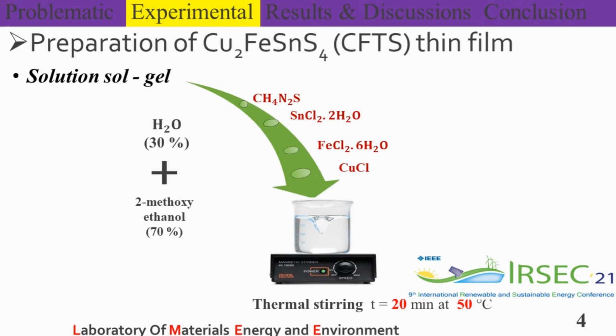Firstly, I will present the part of experimental section concerned to synthesis of CFTS thin film solar cells by sol-gel spin coating technique. The precursors used to prepare the sol-gel solution were copper chloride, iron chloride, tin chloride, and urea dissolved in a solution of methoxyethanol and deionized water. The solution was stirred on a hot plate at 50 degrees C for 20 minutes. The bronze sol-gel solution was formed. After that,